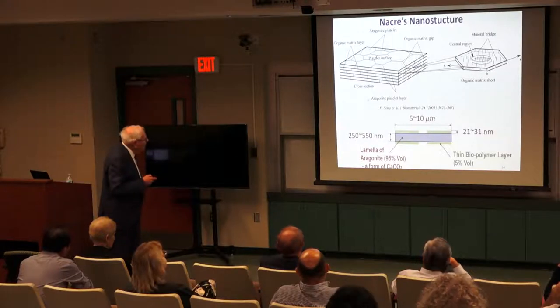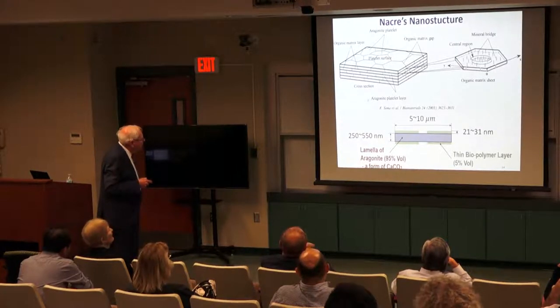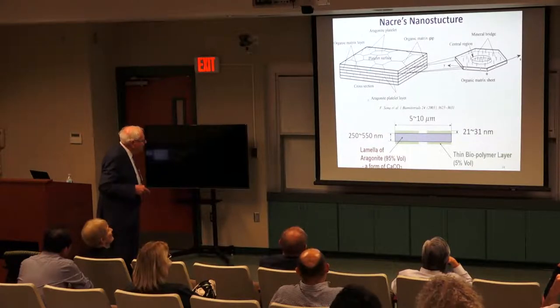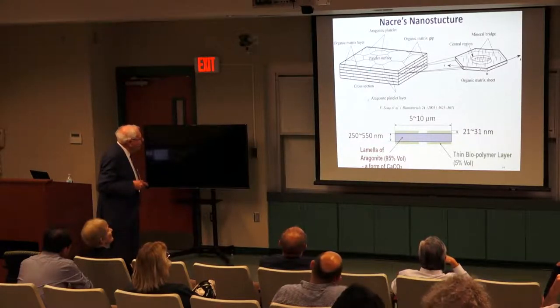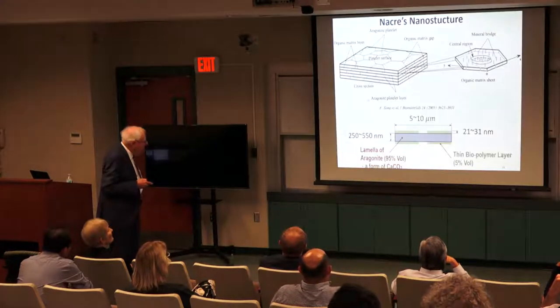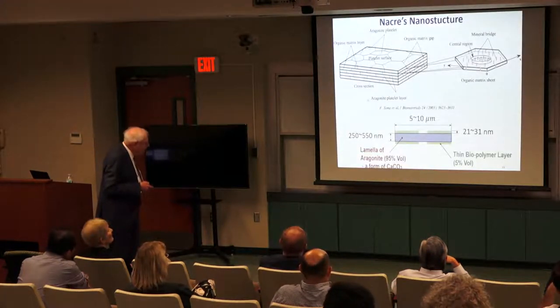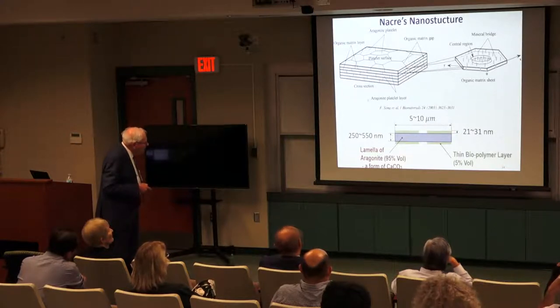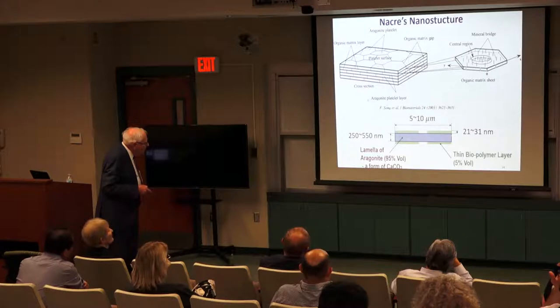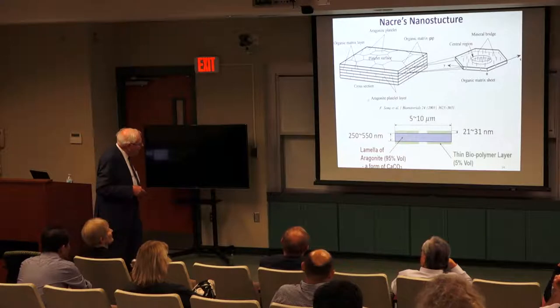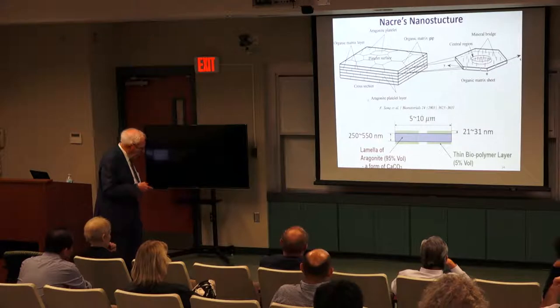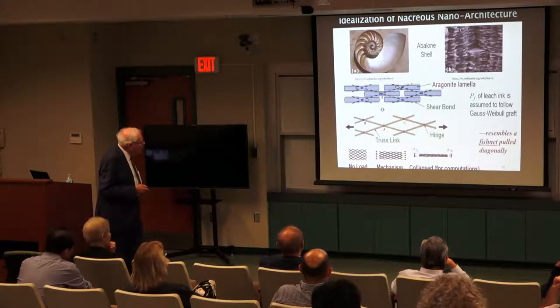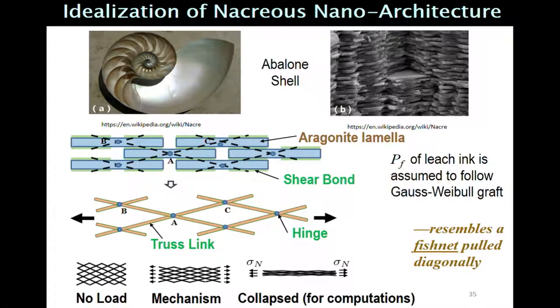And these animals produce a nanoscale microstructure consisting of rigid platelets of aragonite, something like this, which are typically about 5 to 10 micrometers long, about 20 to 30 nanometers wide, so they are longer than shown, and they are bonded by a biopolymer, a very thin layer, a few nanometers, 20 nanometers. So how to simplify it? Here is a micrograph of this structure. This is a nacre abalone shell.